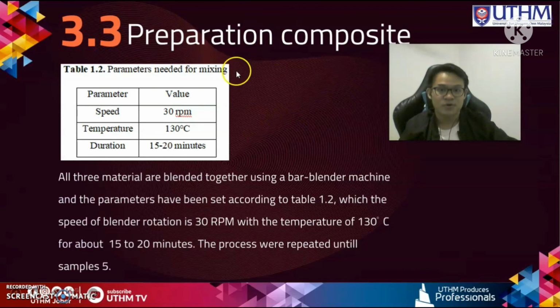Next subtopic is the variations of the composite. As we can see, the table here shows the parameters needed for mixing. All 3 materials are blended together using a blender machine, and the parameters have been set according to table 1.2, which is a speed of blender rotation of nearly 30 rpm, with a temperature of 130 degrees and a duration of about 15 to 20 minutes. So the process was repeated until 5 samples.